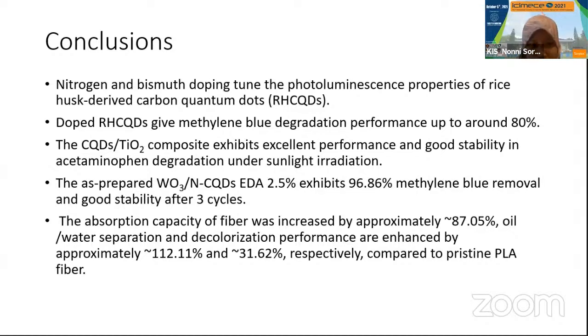And the decolorization performance improved by around 31.62%. Right? For the oil and water separation, we can improve the performance of the fiber by more than 100%. So from here, we can see that the incorporation of the carbon quantum dots into the photocatalytic agent matrix is not only limited to photocatalytic degradation, but can also be extended to other types of application, such as oil-water separation.